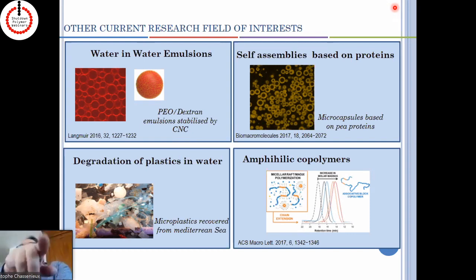So it was with quite a big amount of salt, I mean with an ionic strength which was quite high and which could mimic what you obtain in the body. So I don't think that you have such a big influence of the ionic strength on the result that I've shown you, but the relaxation times can be slightly affected by the ionic strength, which is a result that we have published also quite a few years ago.